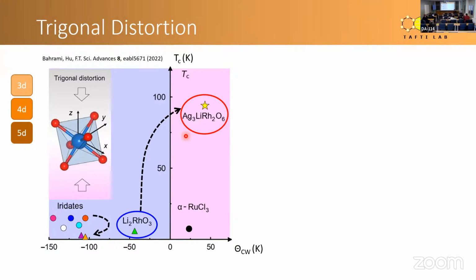So what we learned in this experiment was that there is another very important structural parameter that plays a significant role in this physics. And that parameter is the local distortion of octahedral units in these materials, specifically a trigonal distortion. A trigonal distortion can happen in any octahedral coordination when you take, for example, the top 3 atoms in a triangle and press them against the bottom 3 atoms, in this case, oxygens.